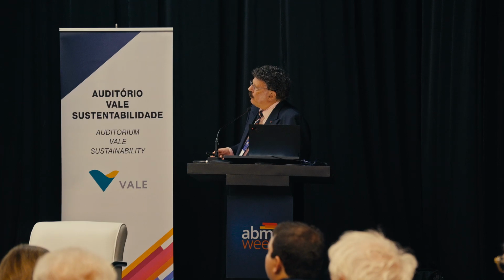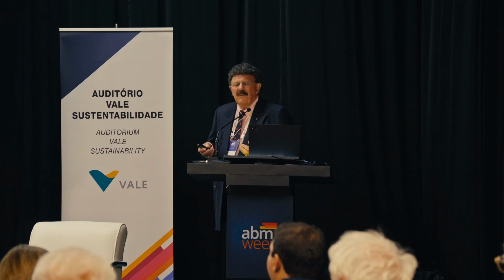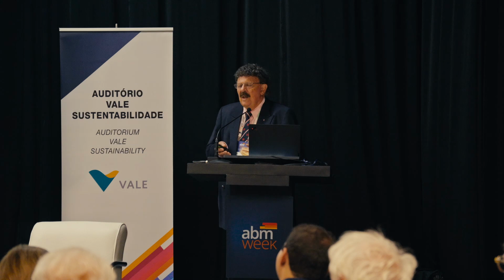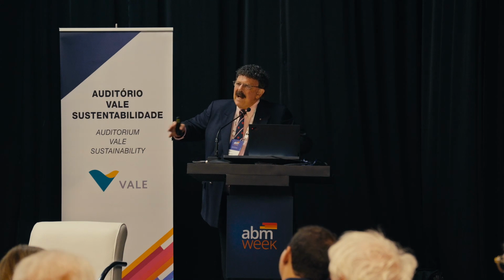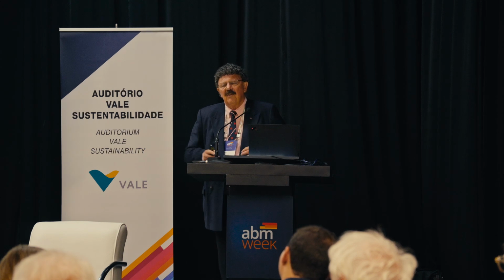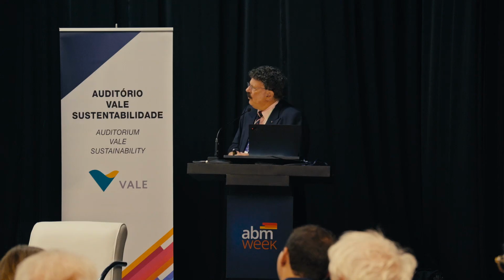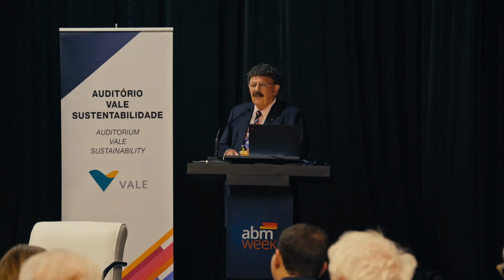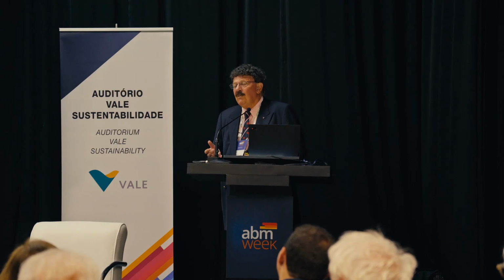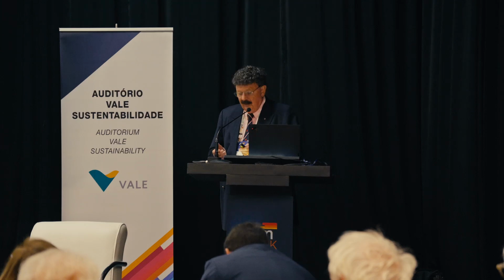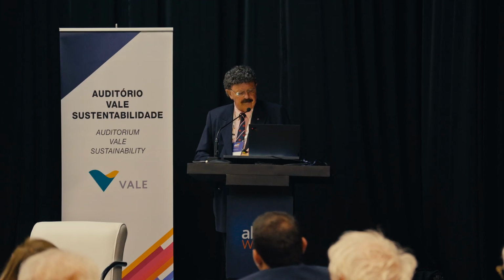And there are amorphous regions here as well. I'm not sure what the amorphous regions do in terms of toughening, but they're another mechanism to give us this sequence of deformation. So these are really, really tough materials. They get tougher at lower temperatures, and they get tougher at higher strain rates, which is very intriguing.